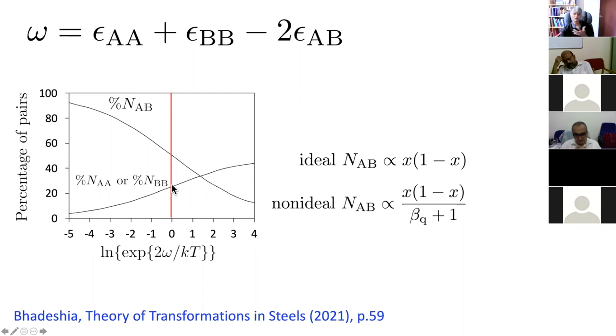As soon as the enthalpy of mixing becomes negative, that means you are favoring unlike atoms to be close to each other, and we get a larger proportion of AB bonds. Okay, it's no longer a random solution, it's more like an ordered solution. And when the enthalpy of mixing is positive, unlike atoms prefer not to be next to each other. So we get a dramatic reduction in AB bonds. So it's possible to calculate a non-ideal entropy of mixing.